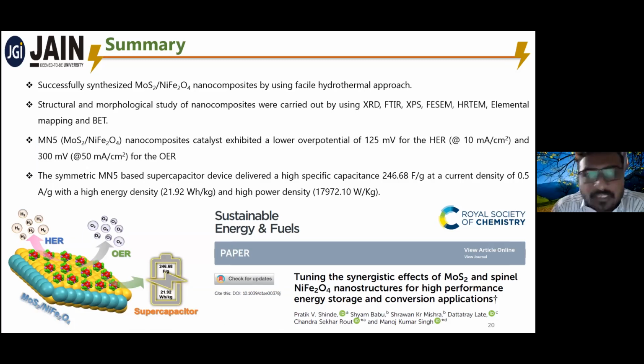So we successfully synthesized our MoS2 and nickel ferrite nanocomposite by a facile hydrothermal approach. We did structural and morphological studies with several analytical tools. The materials are well suited for HER and OER studies. In this nanocomposite, a synergistic effect is created due to the electronic interactions between the MoS2 as well as the nickel ferrite, beneficial for both these applications.